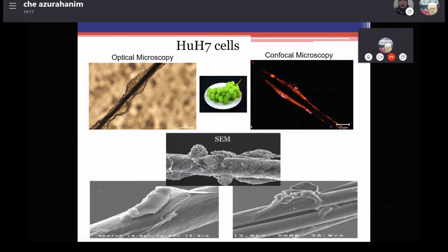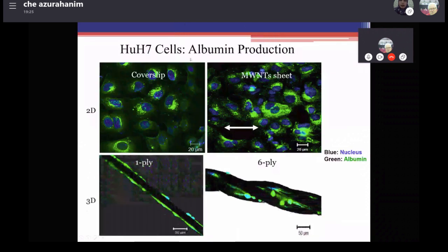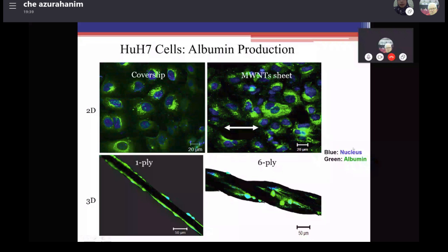For this one, we also check the albumin production. This image shows that the albumin production is much higher, although this one is only images. Actually, I also did another study by checking the amount of albumin secreted by the cells. We found that the cells on the 3D scaffold secreted more albumin compared to the cells on the 2-dimensional culture.